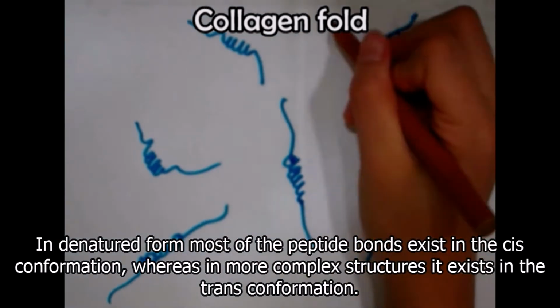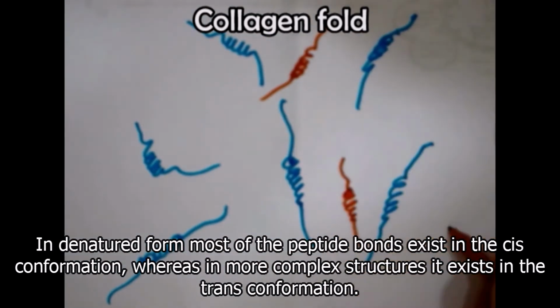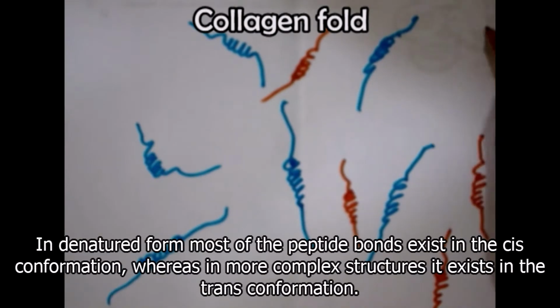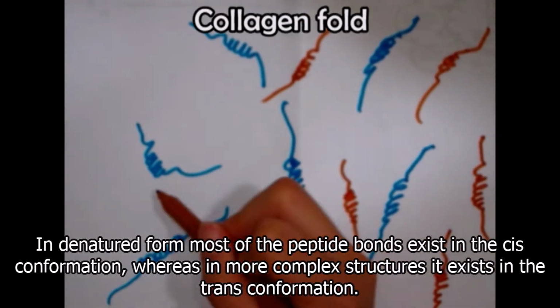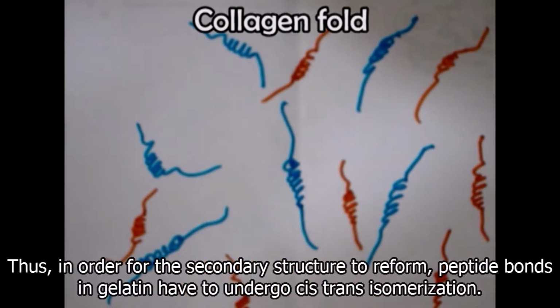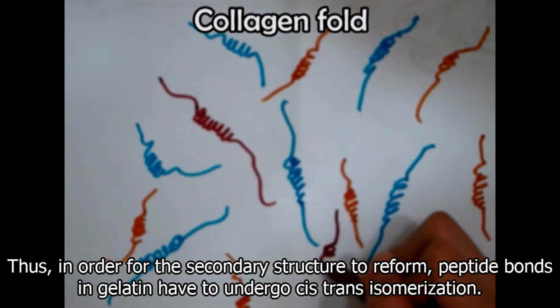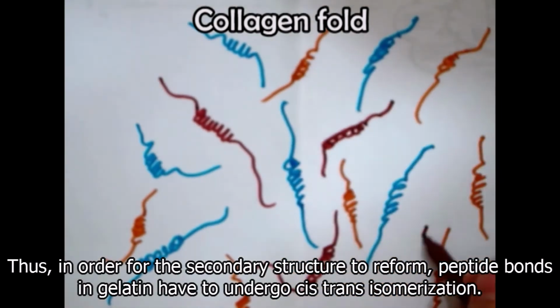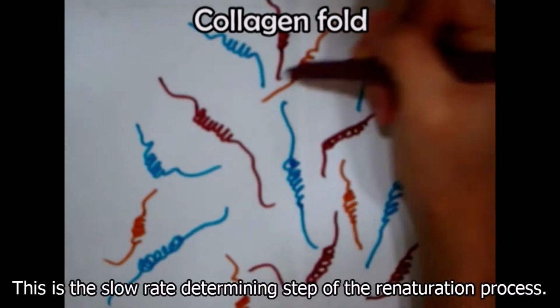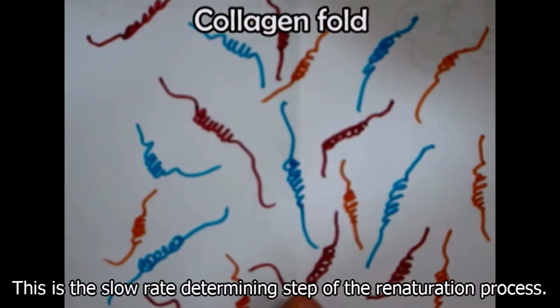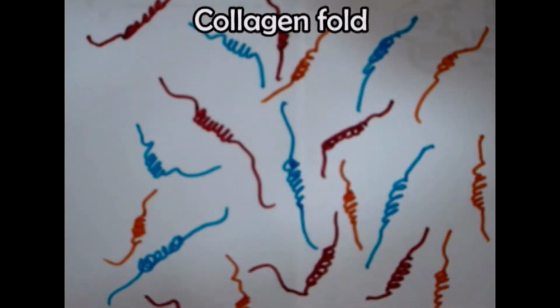In denatured form, most of the peptide bonds exist in the cis conformation, whereas in more complex structures, it exists in the trans conformation. Thus, in order for the secondary structure to reform, peptide bonds in gelatin have to undergo cis-trans isomerization. This is the slow rate-determining step of the renaturation process.